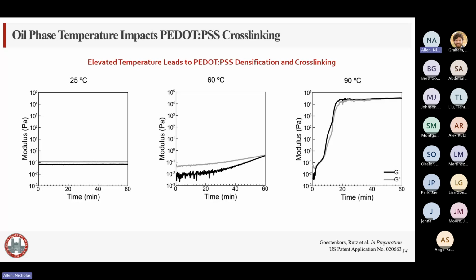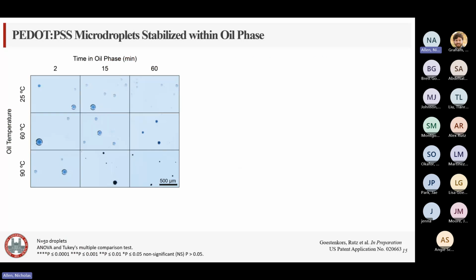So I conducted 3 emulsion conditions, at 25, 60, and 90 degrees Celsius, and monitored the aqueous droplet formation over 60 minutes in these 3. And as you can see, at 15 minutes, in the 90 degrees Celsius condition, those aqueous droplets get less transparent and much smaller, which we thought was indicative of cross-linking taking place in emulsion. However, we didn't see that change at 60 or 25 C. And indeed, when we measured the diameter of all 3 conditions, we saw a significant change at 90 degrees Celsius, but non-significant at the others.